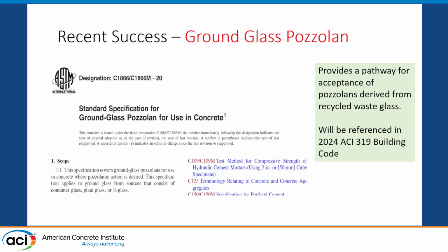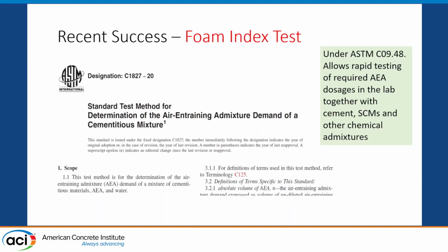We got the ground glass pozzolan standard in 2020, which allows municipal waste glass recycling operations to process and grind the glass and make it into a pozzolan. There's about, I think, 3 or 4 plants in the U.S. operating now, but the total capacity is still under 1 million tons, so it's not a huge quantity. And there are some issues with using it in terms of its high alkali content, in terms of ASR issues.